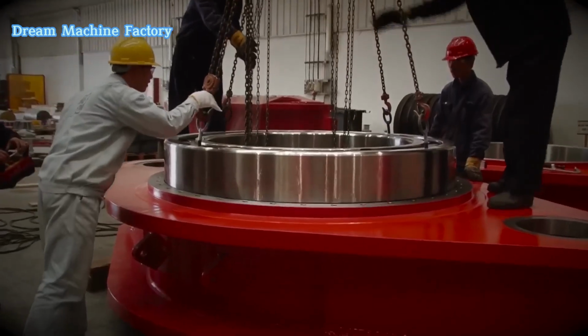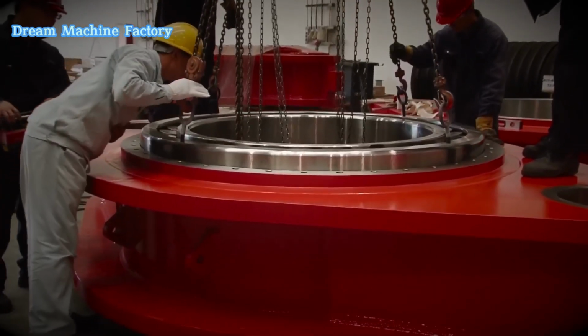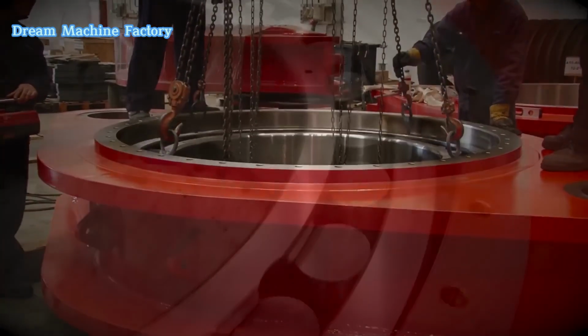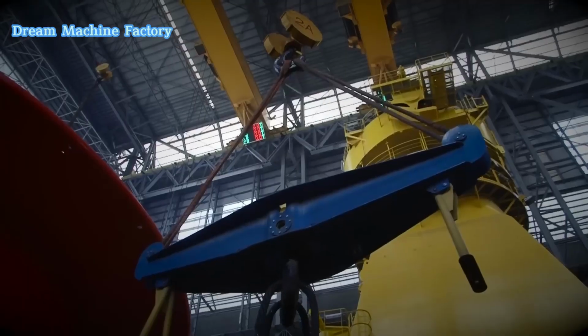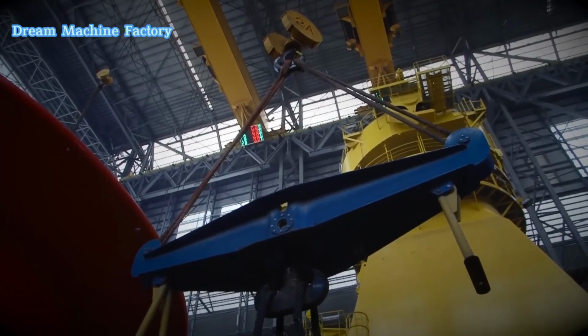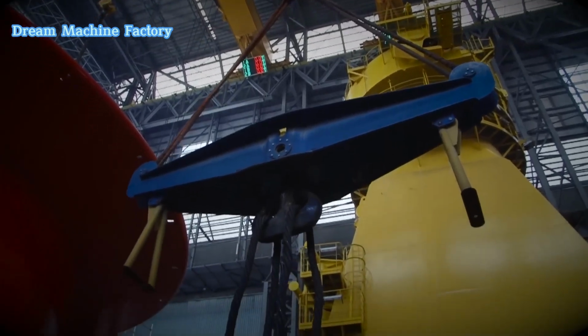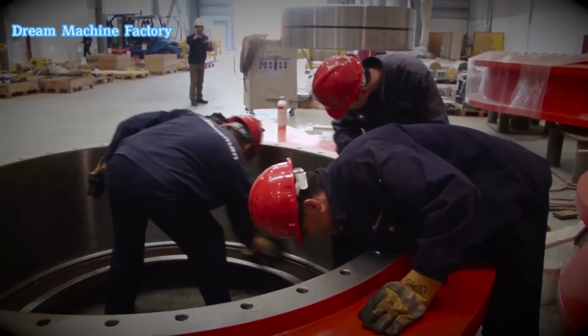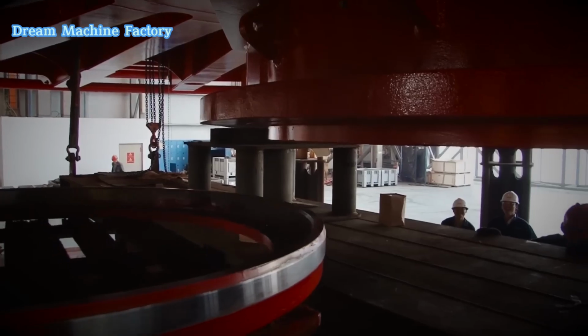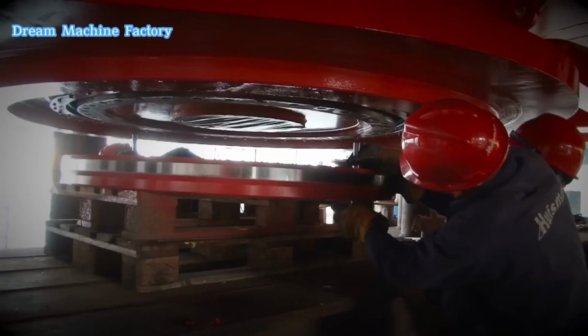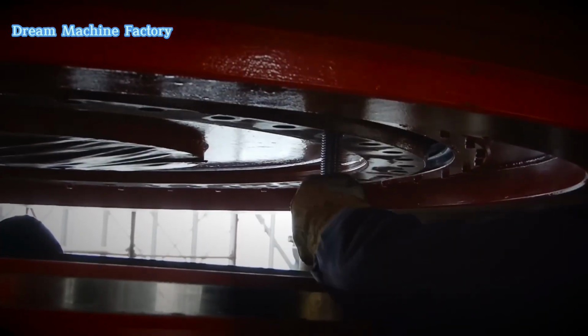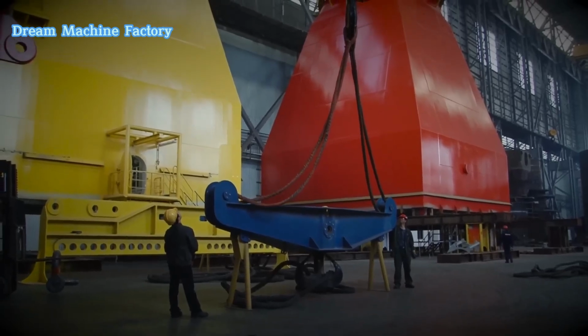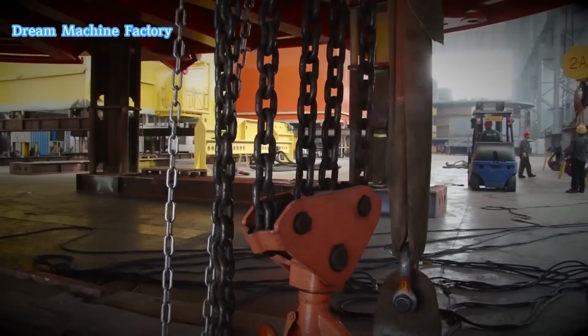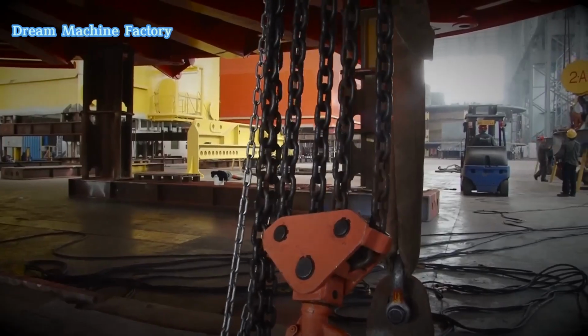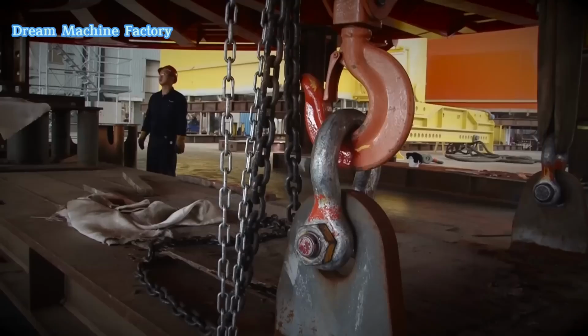Mounting large spherical roller bearings requires precision to prevent damage and ensure longevity. The bearing seat and shaft must be thoroughly cleaned before installation. For a tight fit, the inner ring is heated to 80 to 120 degrees Celsius using an induction heater or oil bath, allowing it to expand for easy mounting. After cooling, it securely grips the shaft. Proper lubrication is applied, and housing alignment is checked. Final inspections include clearance measurements and smooth rotation testing, ensuring optimal performance under heavy loads.